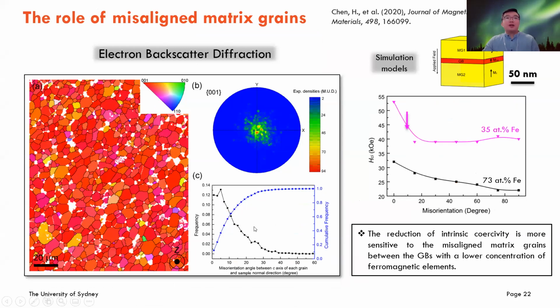And the third important factor is not only the grain boundary, but also the neighboring matrix grains. This neodymium iron magnet has a strong texture for retaining high remnant magnetization. So the red grains here all have one strong texture, but you can see some yellow ones and some pink ones here, which we call misaligned, because they are somehow derailed from the main direction here. And the adjacent grain boundary, whether it's ferromagnetic or non-ferromagnetic, will strongly affect the nucleation field here, which you can see on the right side.